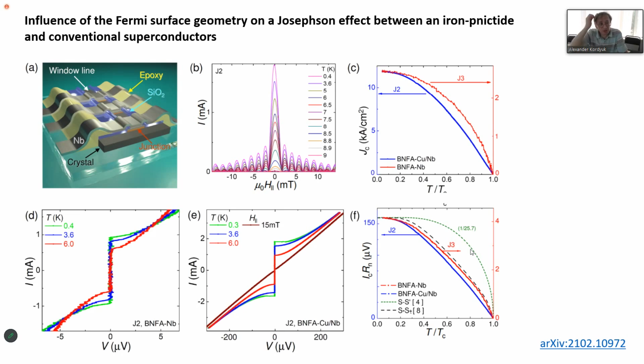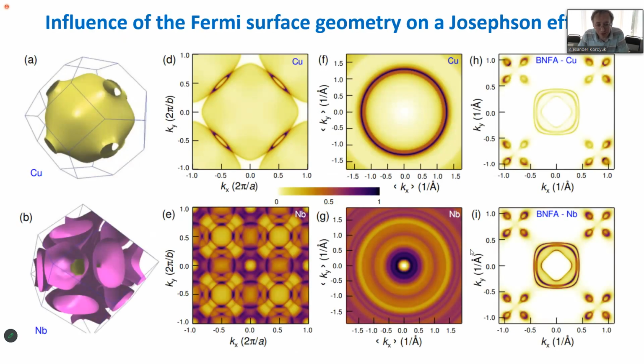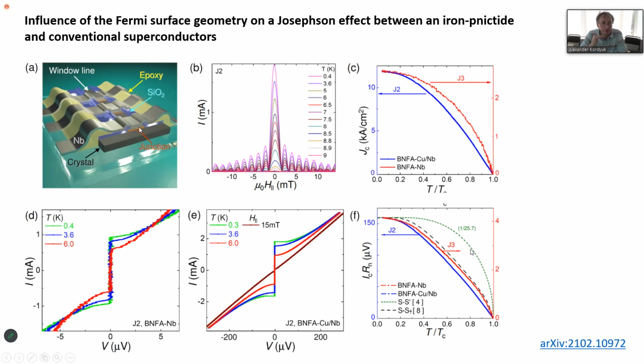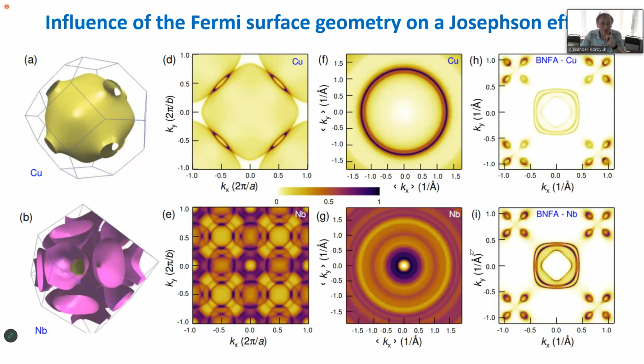But what was most interesting about it is that Alexei Kaleniuk from our department, he did it in Stockholm, and he spent a lot of time to invent this technology to do it. And he found an interesting effect: he put a thin layer of copper in between niobium and the iron-based superconductor single crystal. The expectation was that the junction would be better, but the parameters would be lower. But the parameter ICRN, which is proportional to the superconducting gap for a normal superconductor, increased 40 times. And this increase is related with the Fermi surface, as we understand now.